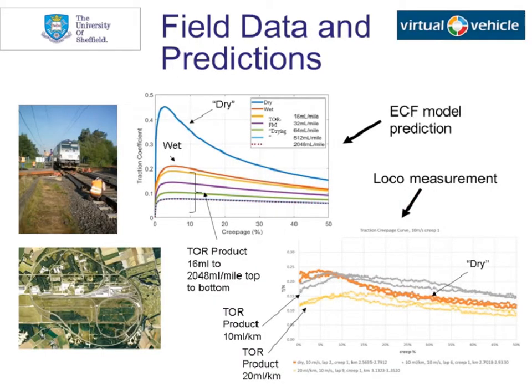So we're very lucky to be able to obtain some locomotive data. So this is a locomotive running over track where the same top of rail product had been applied directly to the rail head. So the graph at the top shows the predictions from our newly tuned extended creep force model. So you can see traction coefficient against creepage, and then the same measurements at the bottom from the locomotive. You can see there's quite a difference between the nominally dry values. Well, obviously our dry values in our prediction are for dry values. Within the field, it was actually very difficult within this testing environment to achieve dry.